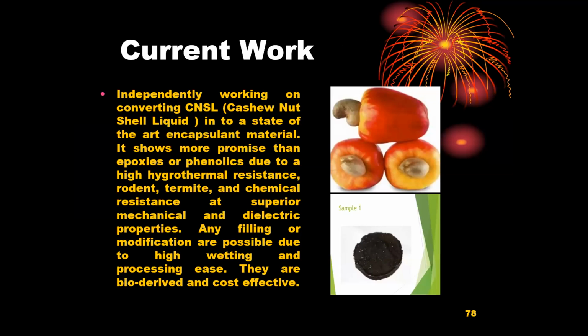Current work, which is not from the SPEL work, I'm just adding a slide. I am looking at cashew nut shell liquid as a potential material for encapsulation, as it is rat resistant, termite resistant, and hygrothermally very stable compared to some of the basic epoxies or phenolics, and it has good adhesion characteristics, and it is easy to process with phenol formaldehyde or acid curing or alkali curing. They are bio-derived and cost effective. A liter of cashew nut shell liquid costs you $1 or $2 in US currency, and this shell liquid, from the shell from which you take the cashew nut, is available in some of the cashew rich areas. We buy them, and we can produce a lot of products for a very cheap price, and they can be cured at 120 or 180 degrees Celsius.